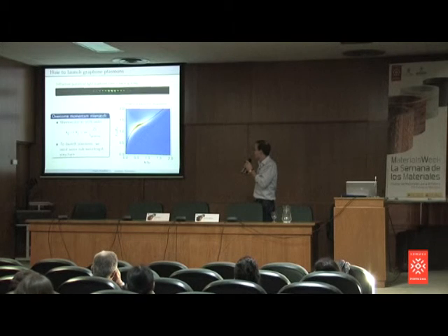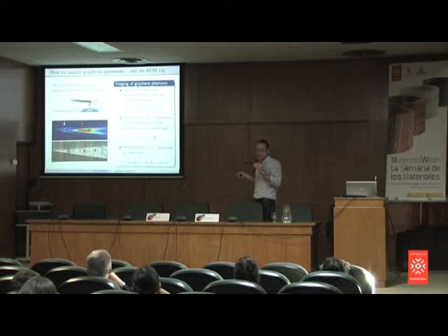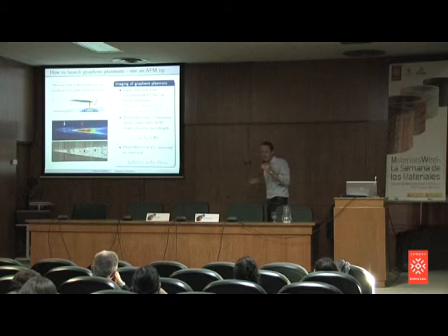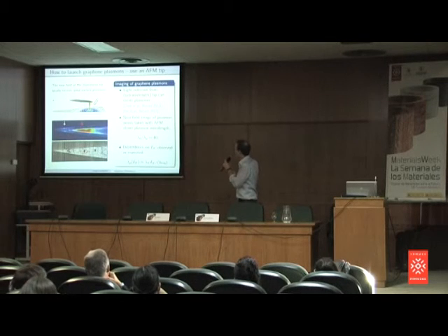And the first thing here was this here. Well, good, 2 groups, let's say. But what they do is they take light here. Here is graphene, and they shine it on the tip of an atomic force microscope, an AFM microscope. And this tip is metallic and very sharp. And the light has a wavelength of 10 microns, let's say. That's in the terahertz somewhere. And the tip is much smaller than this.